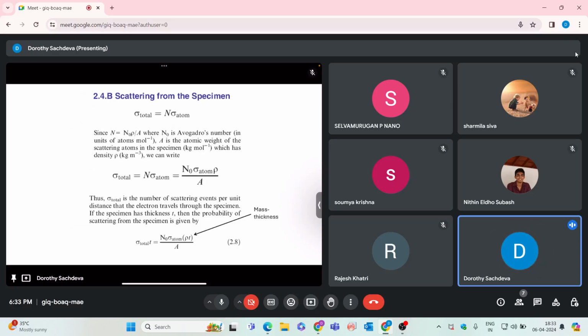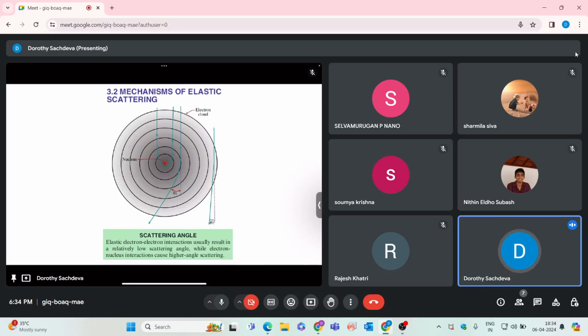Then we have these elastic and inelastic scatterings present in the TEM. So elastic scattering is basically what? You have your nucleus present at the center of your atom and electron clouds all around it, and your electron beam is coming and it is being deflected by the interaction with the nucleus. And if it is very far away from the nucleus, then it won't have much contribution from the nucleus and it will go straight like this. And if it is going in between, then it will be slightly shifted by a certain angle from the incident beam direction. So scattering is basically what? It changes the direction but not the energy.